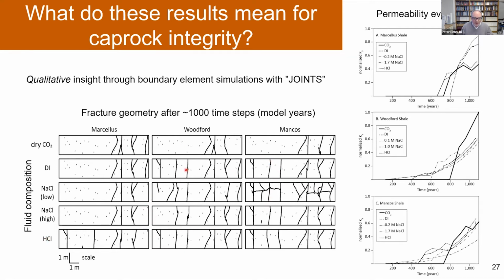They look maybe very similar to you for the most part, but it's interesting to then see, and this is also something that JOINTS allows, it can calculate a fracture permeability across those fractures. And you can show this over time, model time, as a function of the different environments and for the different shales. And there we see differences. So for instance, if I take the Woodford Shale, which is clay rich,